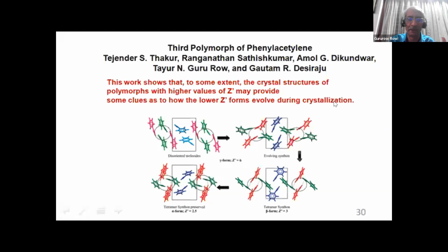evolve during crystallization. So when crystallization occurs, a large number of molecules, 10 to the power of 20 molecules, come together, and these molecules now form assemblies, and these assemblies will follow certain rules, which are essentially nucleation rules, and those rules probably are verified or probably are violated, depending upon the conditions in which we do the crystallization. So from an assembly of a very large number of Z prime values, we can arrive at properly arranged Z prime values. By Z prime value, I mean the number of molecules in the asymmetric unit. The number of molecules in the asymmetric unit started in this case. All these are crystal structures in the in situ cryocrystallization process of phenylacetylene. Again, a liquid at room temperature.